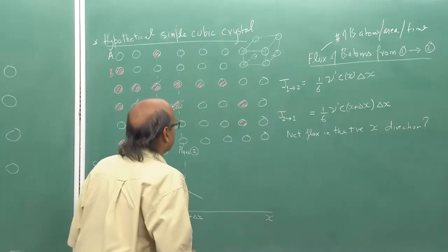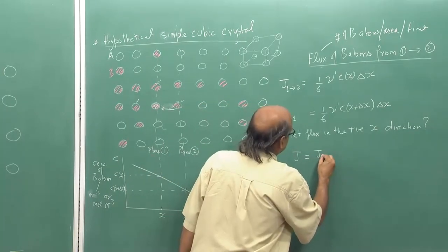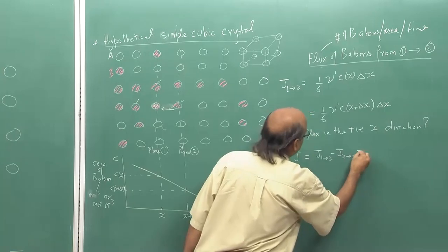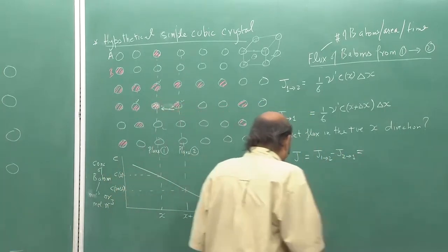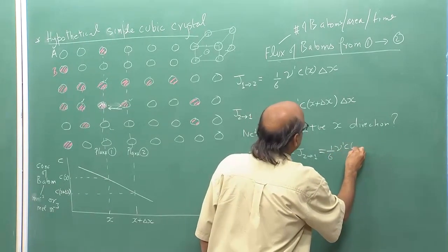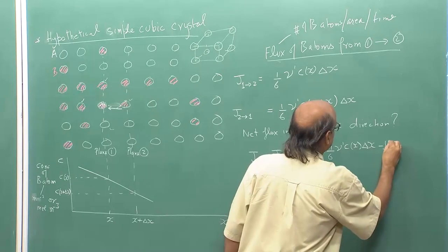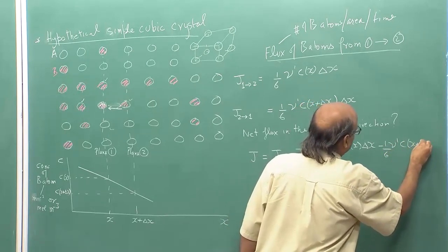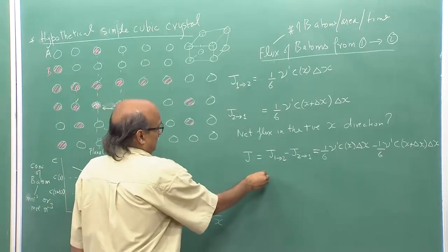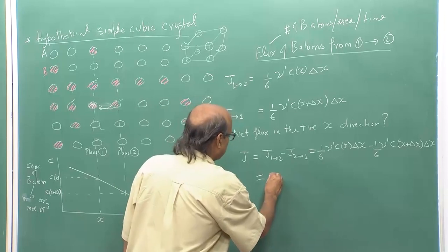So, the net flux in the positive x direction, let me call that J. Then clearly this is J 1 to 2 minus J 2 to 1. If I write this, this is simply 1 by 6 nu prime C(x) delta x minus 1 by 6 nu prime C(x plus delta x) times delta x. This is equal to, and let me rearrange it a little bit and write it like this,